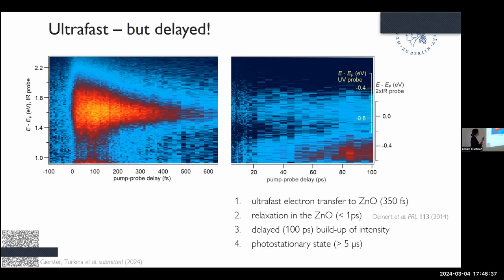And now comes the important thing. The electrons leave the molecule. They are gone. If we don't detect them here, after 1 picosecond the signal is gone. The electrons are in the bulk of the zinc oxide. This is why we do not detect them anymore. Then it's known that the relaxation to the conduction band minimum occurs very quickly in zinc oxide. But they are not there for 100 picoseconds. And then they come back to form a very long-lived state. They come back to the surface. So there must be an attractive force that pulls them back.